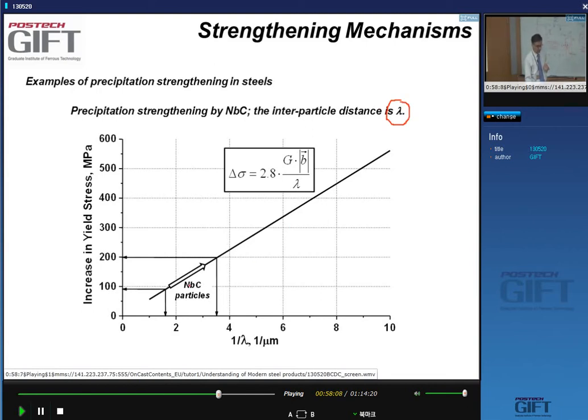So if I have particles with the same size, say that ideal 5 nanometer size, then a reduction in the interparticle distance basically means that I have more particles or a higher volume fraction. You will see that there is a linear relation now between the strength and the inverse of the interparticle spacing. Okay.